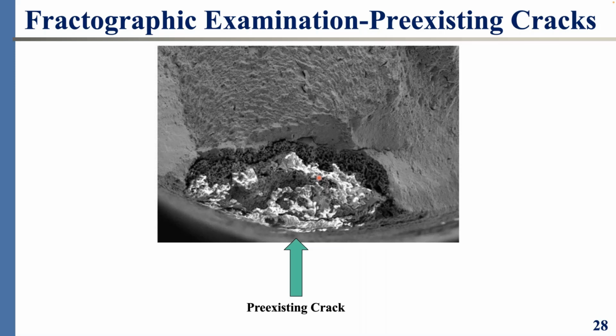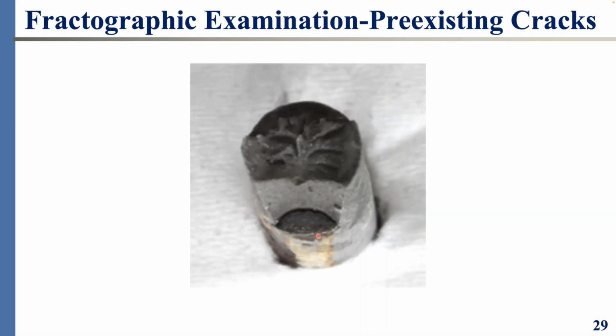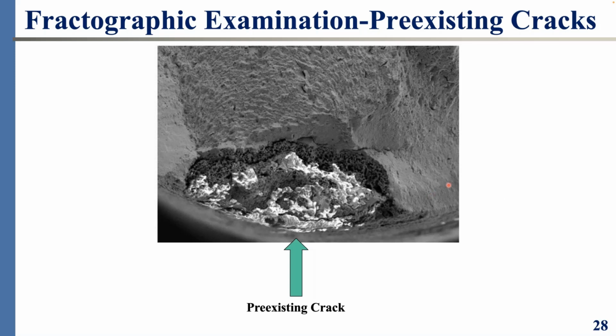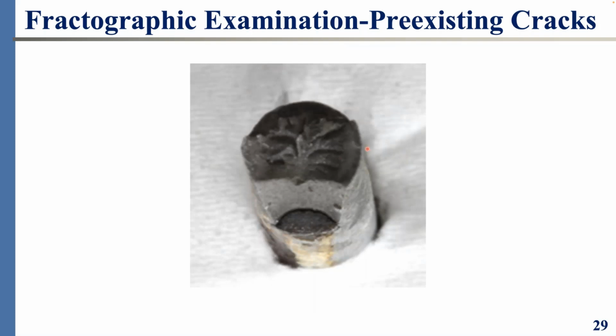So you see here the thumbnail crack. Here is actually this picture. It is no mystery. It is the cross section, the circular cross section of the wire that we see here. And of course, this is the cracked part. And here is the crescent shape or the thumbnail crack, where you see the wire is maintaining its full cross section, embrittled, no necking, no sectional loss. The crack goes into mode 1, which is perpendicular to the stress field, which is along the longitudinal axis of the wire. And then when it reaches a critical crack depth, it splits along the grain boundaries, and then the fracture happens on that upper surface.